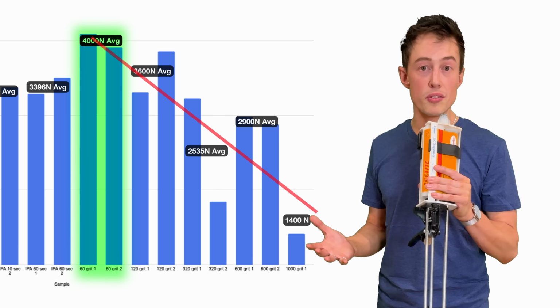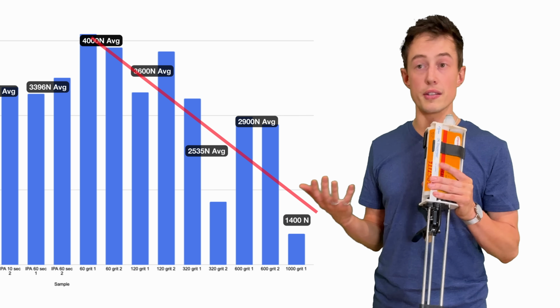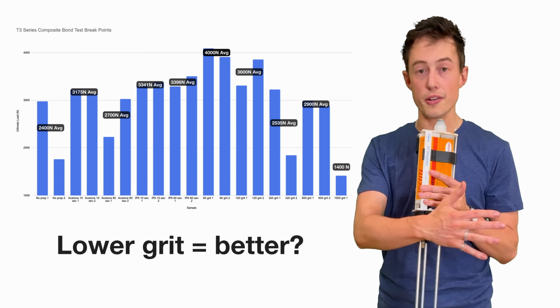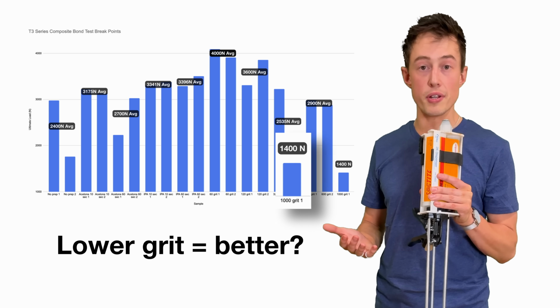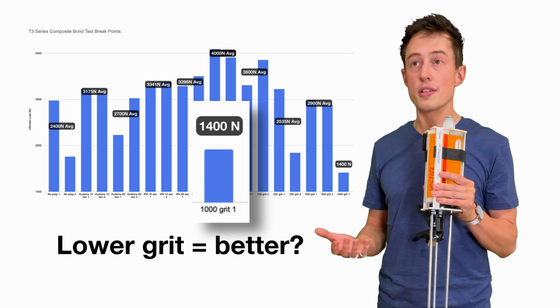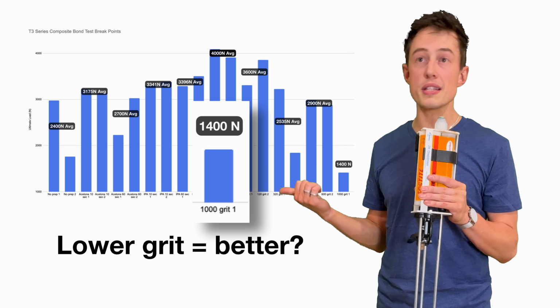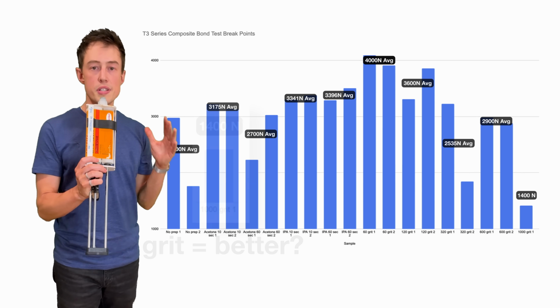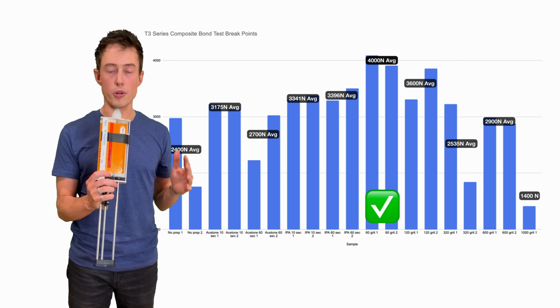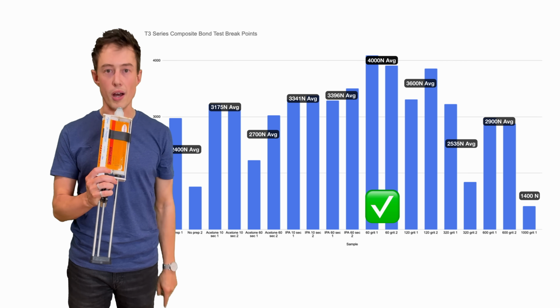It's pretty easy to look at this data and come to the conclusion that lower grits must perform better than higher grits. Once you get up to 1,000 grit, we're essentially polishing the part, so it's no surprise that it broke at a measly 1,400 newtons. So far, 60 grit seems to be our strongest performer, so let's dive deeper and find out why.